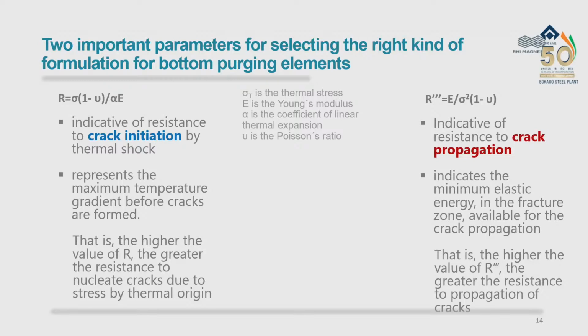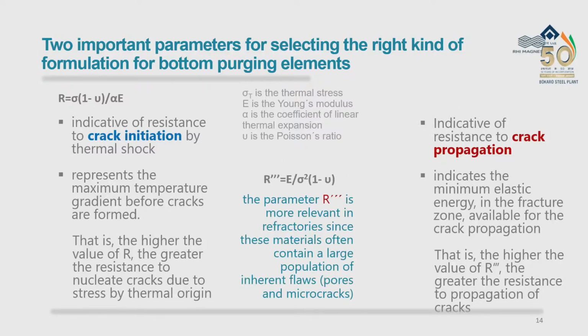And coming back to R triple dash, this is basically a resistance to crack propagation, because every crack needs a certain amount of minimum elastic energy in order to propagate in the fracture zone. That means higher the value of R triple dash, the greater will be the resistance to propagation of cracks. But as a refractory manufacturer, what matters is the R triple dash, because it is more relevant in refractories, since these refractory materials by inherent nature have a large population of inherent flaws, which are pores and micro cracks. So for us, R triple dash is more important than R.